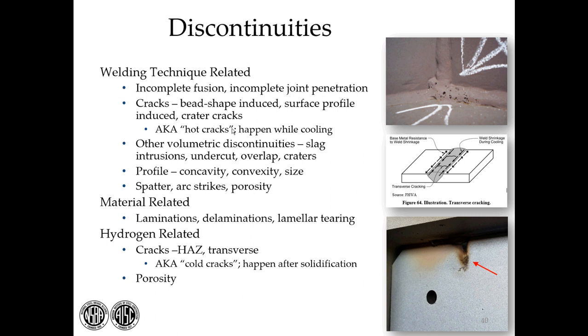And typically these have to do with either welding technique or how you set up the weld itself. There are other volumetric discontinuities such as slag, intrusions, undercut, overlap, craters, etc. Profile, you have to have the right profile. And then things like spatter and arc strikes. This is an arc strike. The code does not allow arc strikes or spatter, and it speaks to the requirements for profiles and the allowances for other kinds of discontinuities. So D1.5 addresses all of these, and these are all the kinds of things that can happen during welding. There can also be problems with material, and D1.5 addresses those also. Laminations, laminar tearing that can impact your weld.